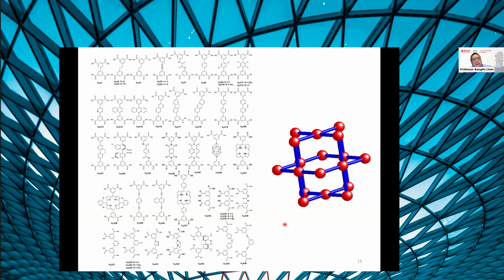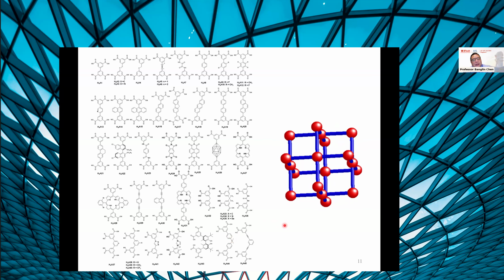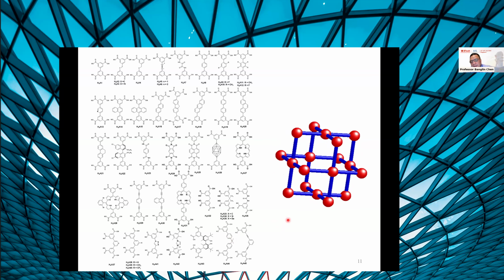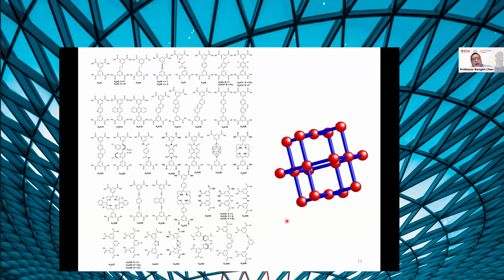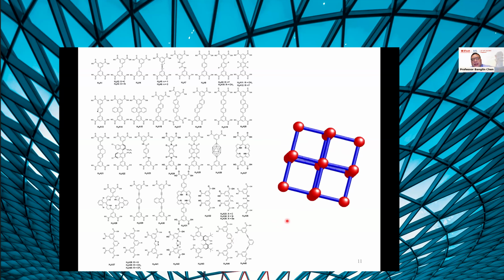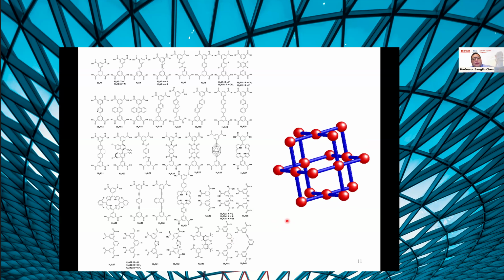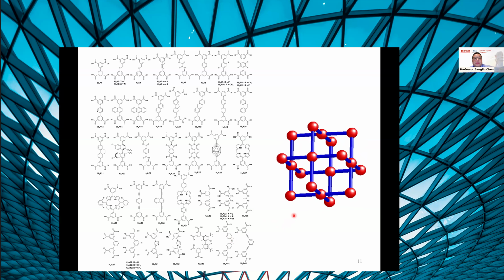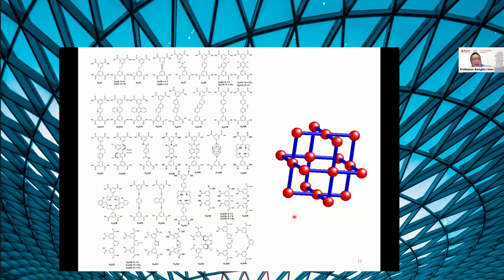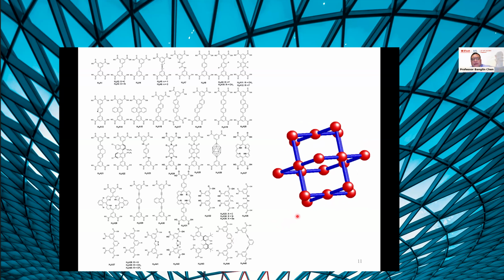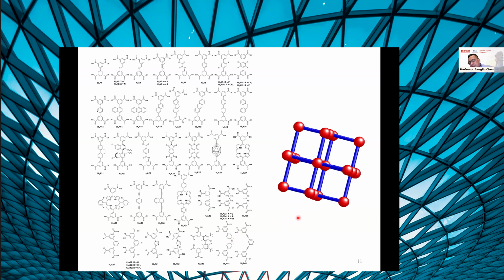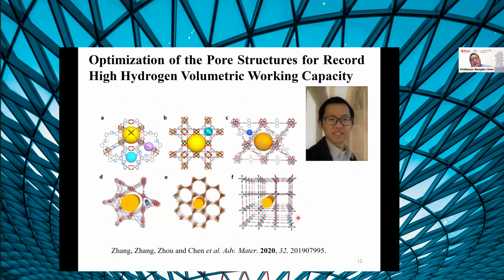But under this low temperature, 77 K and 100 bar, there is a limitation because we still need low temperature, which means we need to cool down, use liquid nitrogen for hydrogen storage. And recently, we realized that for traditional MOF material, there's a limitation for their hydrogen capacities.